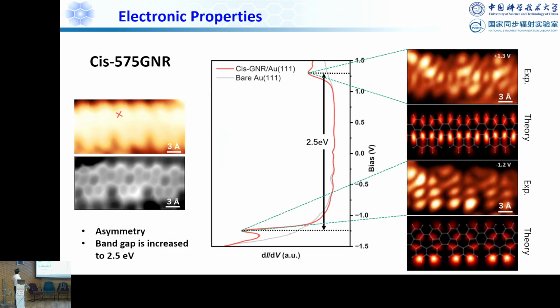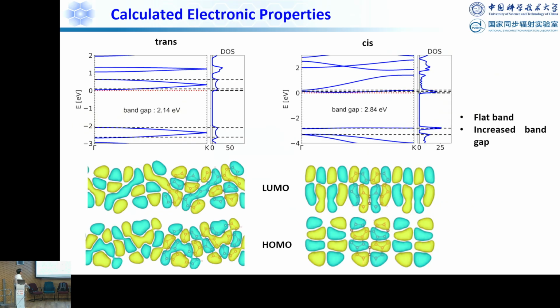And then if you do the cis, the cis structure is like this, and the AFM tells it is a cis. Now this becomes asymmetric, and the band gap increases to like 2.5 eV, and this is the state mapping, and it's also consistent with the calculated result. And the DFT calculation for the freestanding ribbons indeed tells you that this band gap opens up from trans to cis. In addition, you can see that this now forms a flat band on both sides, on HOMO and LUMO. Okay, and I think this is different from what you observe in the 575.